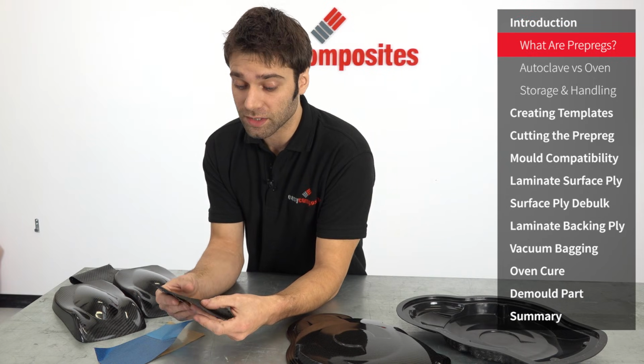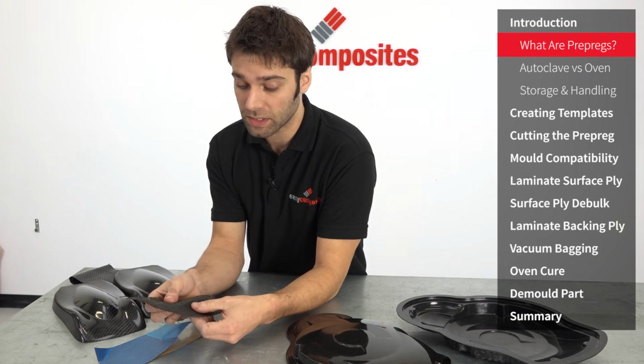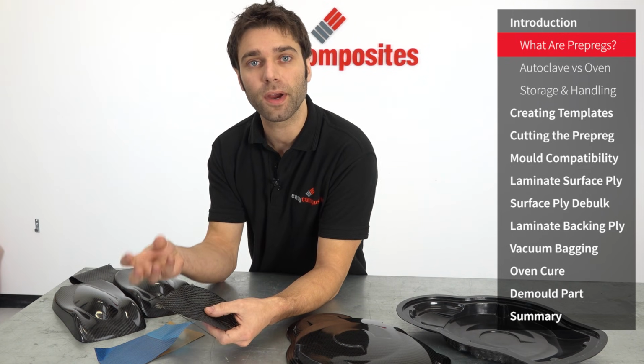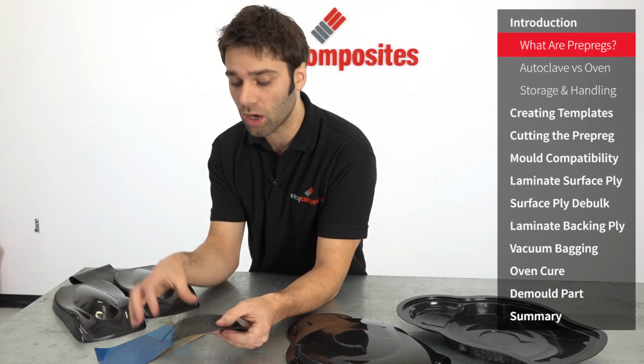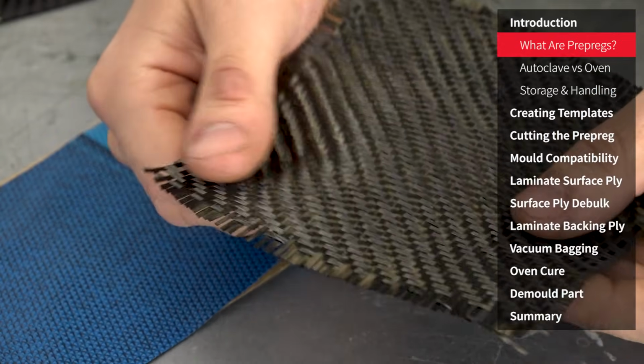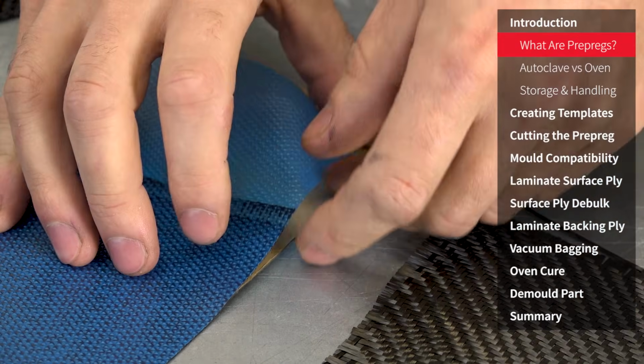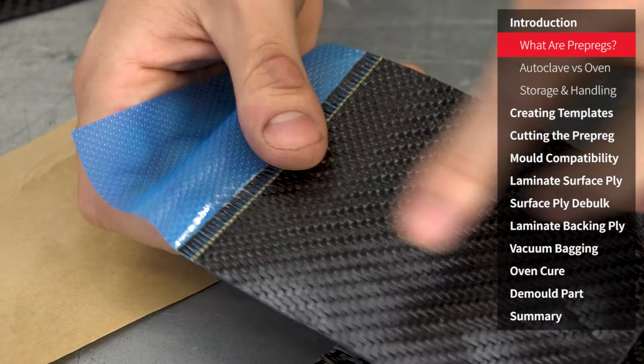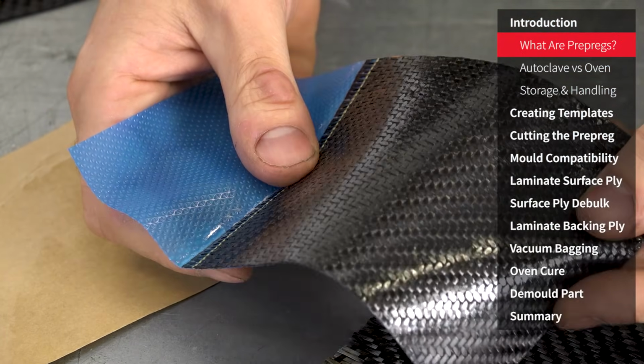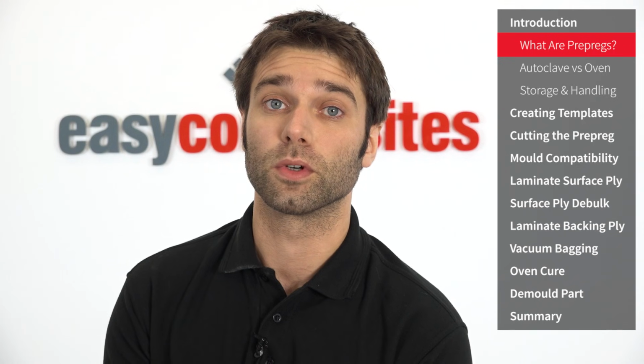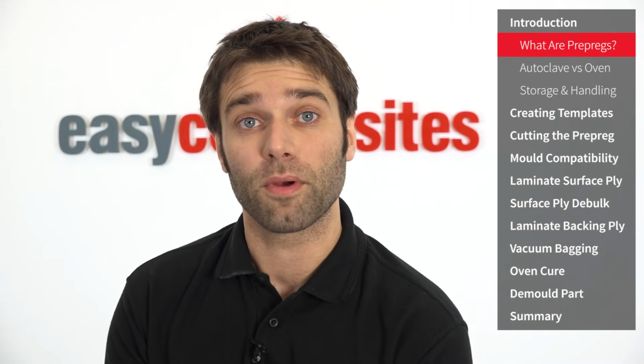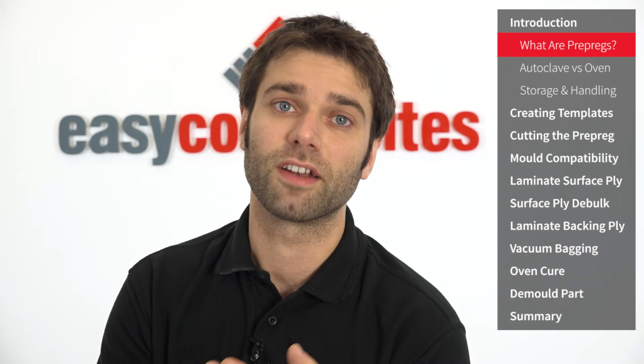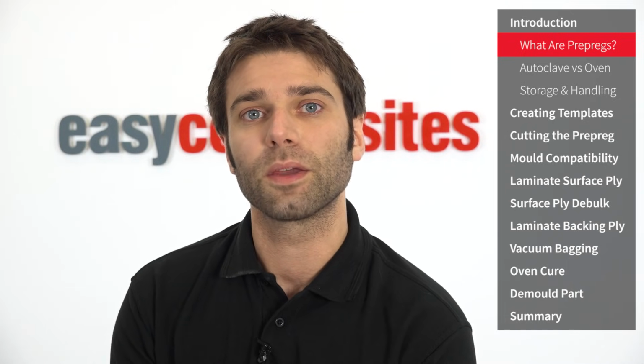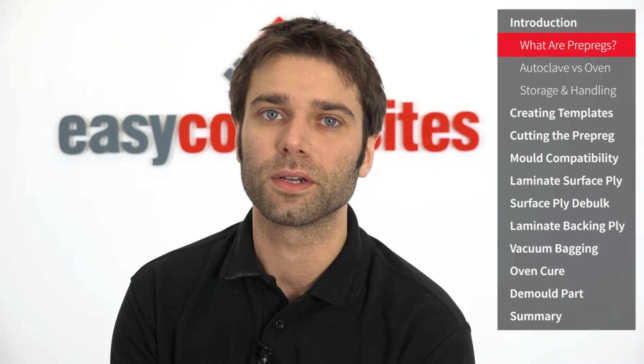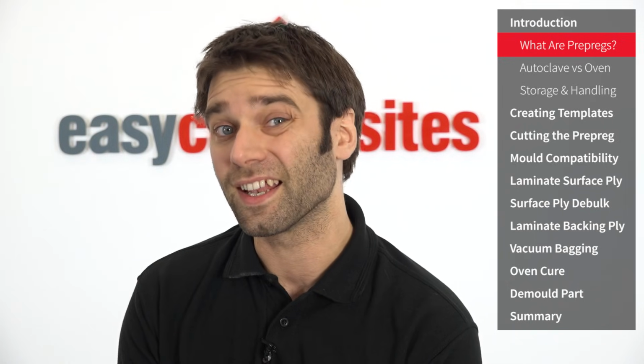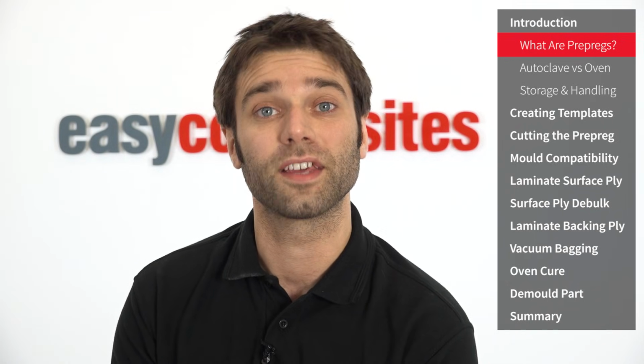Simply put, pre-pregs are just conventional dry reinforcements like this carbon fibre that have been pre-impregnated with a resin that already has the hardener in. So here we have the plain dry reinforcement, and then here we have the pre-preg equivalent with the resin already impregnated into it. And because the resin is already combined with the reinforcement like this, to make parts using pre-pregs you only need to laminate the pre-preg material itself into the mould. So there's no handling wet resins like there would be in a hand laminating process or resin infusion process, and within reason it won't start to cure until it's heated.